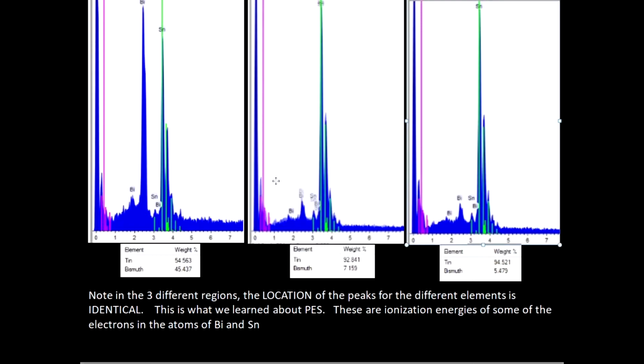These two, the one on the right and the one that I'm overlapping in the middle, had very similar proportions of tin and bismuth. But what about the one on the left, where bismuth was a higher proportion than in these other two? Well, all that should be different is the height of the peaks. And if I slide that over there,